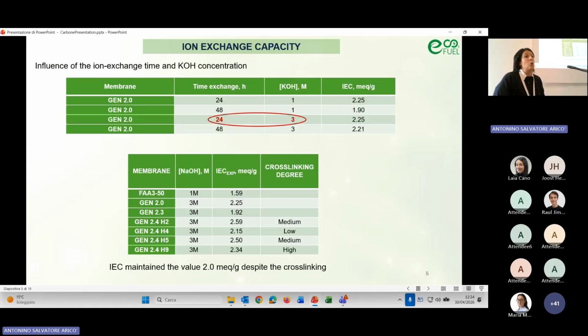Then, with the other generations, it was studied the influence of time and concentration of KOH for activation of the membrane to have the full anion exchange and have all the groups in OH form, and different times and KOH concentrations were tested, and a protocol of 24 hours in KOH 3 molar was chosen, also in accordance with Hydrolite people that developed the membrane. It was also decided to have an ion exchange capacity of about 2 milliequivalent per gram, despite the cross-linking, because this can guarantee a good anion conductivity and good performance.